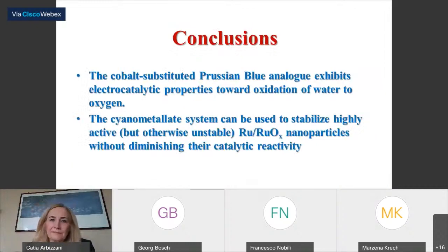For the conclusions, the cobalt-substituted Prussian blue analogs have electrocatalytic properties towards oxidation of water to oxygen, and the cyanometallate system can be used to stabilize highly active but otherwise unstable ruthenium oxide nanoparticles without diminishing their catalytic reactivity.